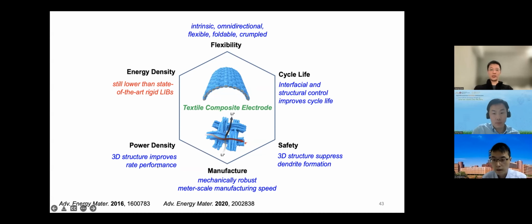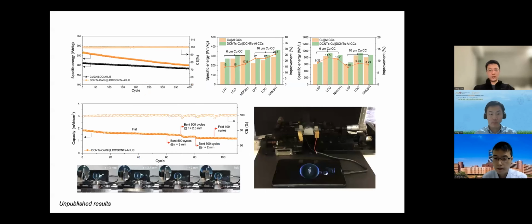The rate performance is pretty good because of the three-dimensional structure. Still, I think in this field, the problem is the energy density. In whatever reports so far, there's no single report showing a better battery in comparison to the rigid counterparts, meaning that you have to sacrifice quite a bit of energy density in order to reach a certain level of flexibility. And these cells are not any better than the existing lithium-ion batteries that we use in the cell phone or in the laptop. I want to show you this last slide,